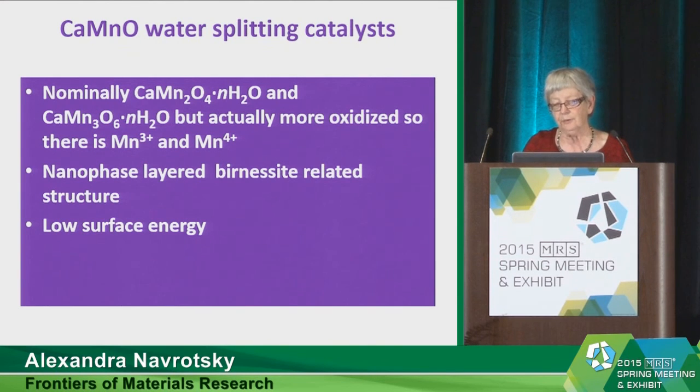First of all, the energy of oxidation reduction in these materials is smaller than that of the Mn2O3 MnO2 equilibrium. That is, one can form mixed valence thermodynamically more easily. Secondly, the materials are layered structures so that they're genuinely nanoscale, and therefore diffusion is not a problem. Thirdly, the materials are hydrated.